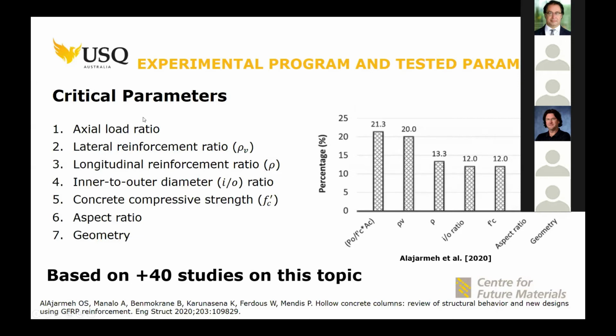So we selected the major or critical ones by waiving the first aspect, which is the axial load ratio, the ratio of the applied load to the ultimate load in the axial direction. We found that it applies to combined actions, not to pure axial, because we need to find out a clear influence of these bars on the concrete columns. So we got rid of that, and we got rid of the last two because they are the least relevant to our study. We relied on the parameters that can affect the constituents of the hollow concrete column. And because of that, we selected these highlighted 4 parameters.